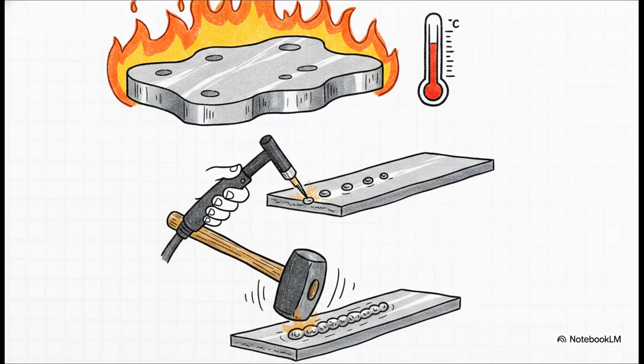It is a major danger zone. So preheat isn't just about hitting a magic number on a thermometer and calling it good. It is about actively managing the entire thermal stress profile across this super brittle casting. You'll want to preheat gray iron somewhere between 500 and 1200 degrees Fahrenheit just to reduce thermal shock. But your actual technique is just as crucial.